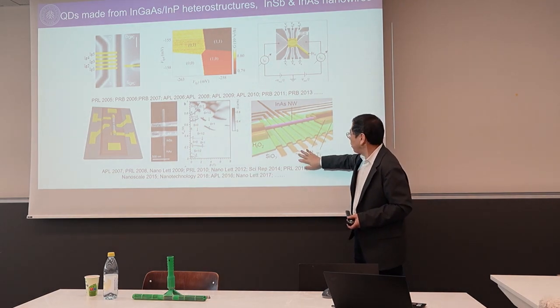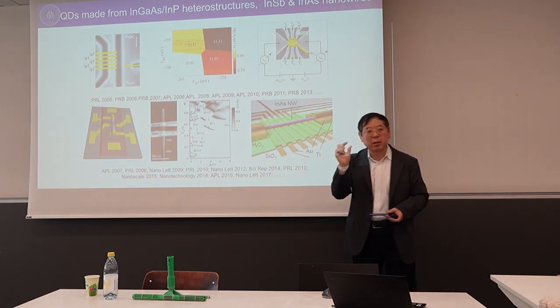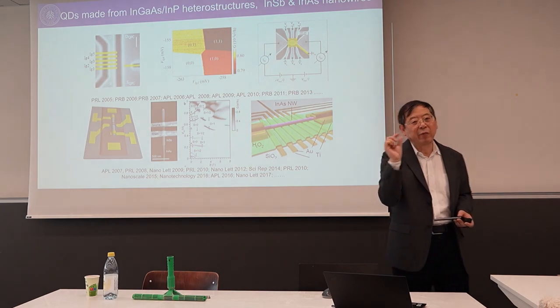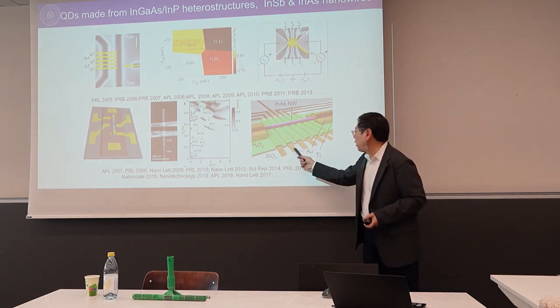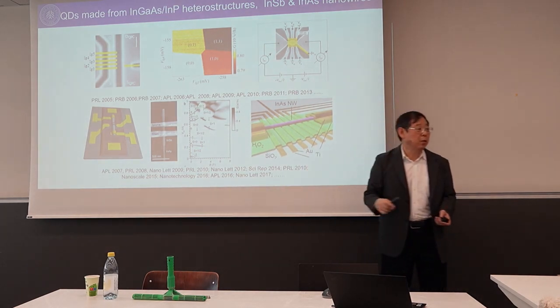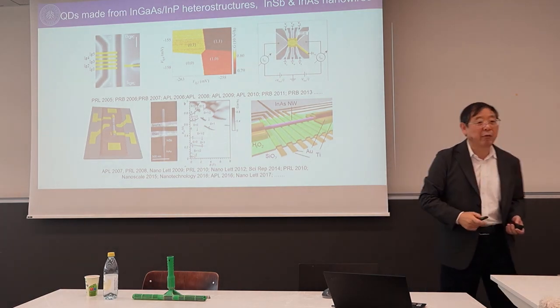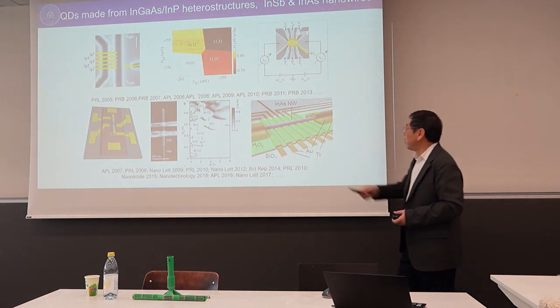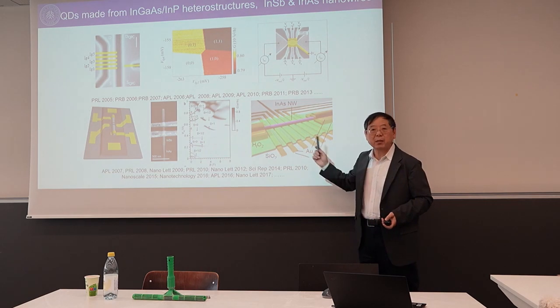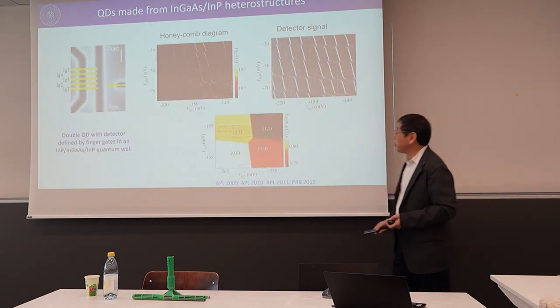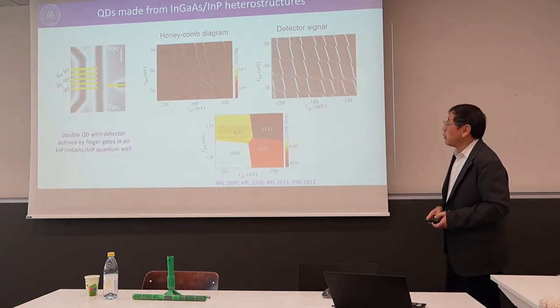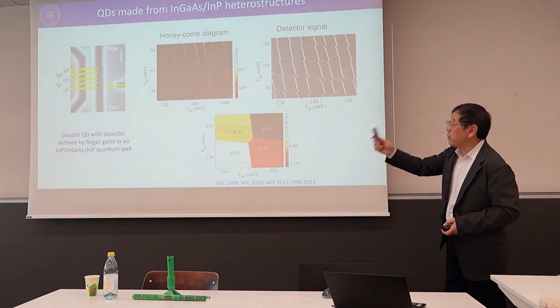So we can use a lot of finger gates. Each of these finger gates is 20 nanometers in width, and the pitch is around 50 or 60 nanometers. So it's very fine technology we are working with, to define several quantum dots and plunger gates on this. So this is just a few examples. This is very nice.